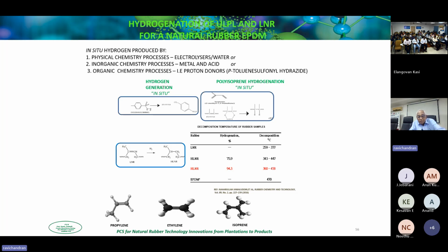You can see in this table that when you get up to 94% hydrogenation, your decomposition temperature is in the range of 360 to 430, as against normal rubber, where the decomposition is 259 to 337. Here, an EPDM, as you can see, is 470. So we are coming up with an alternative to EPDM. So we are challenging that theory.